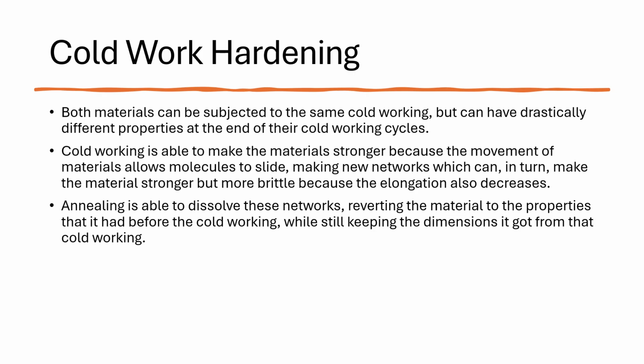Through our results and our calculations, we learned that both materials can be subjected to the same cold working, but they can have drastically different properties at the end of their cold working cycles. For instance, for steel, the cold working introduced high dislocation density, and the dislocations interacted and entangled, which impeded the motion, which raised the strength. Within this, we had microscopic slips, like the atoms sliding, and elongated grains, which increased hardness.